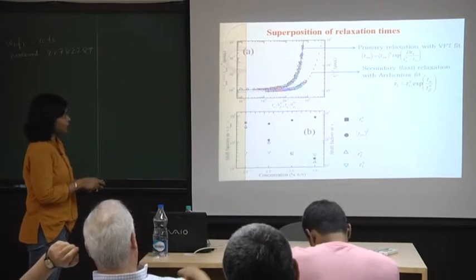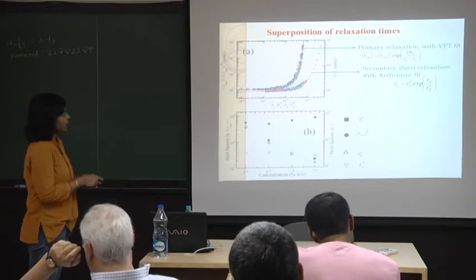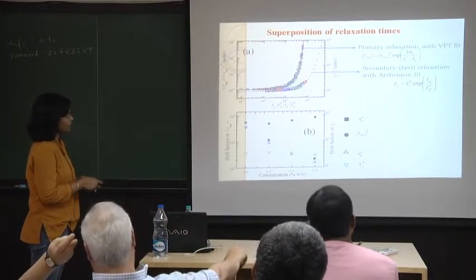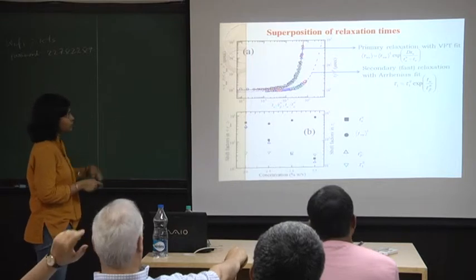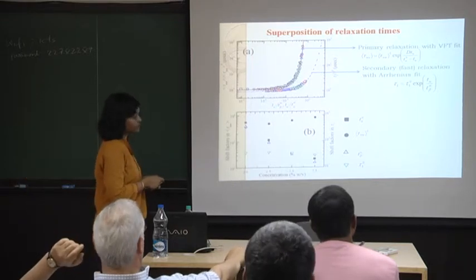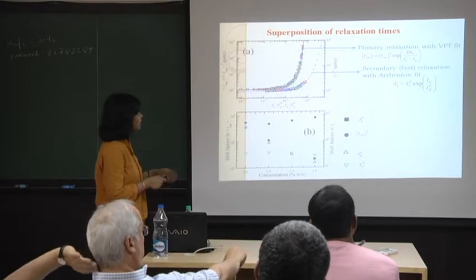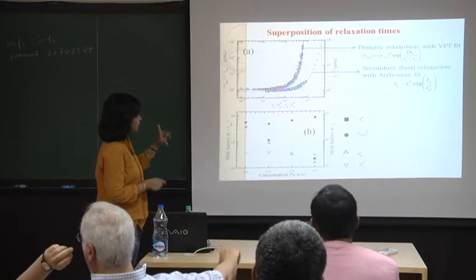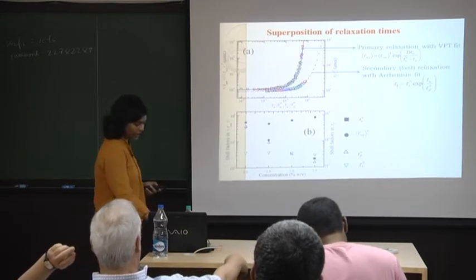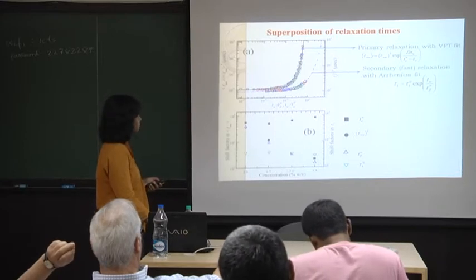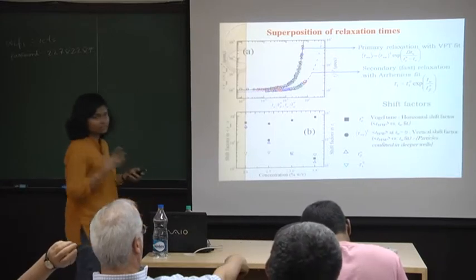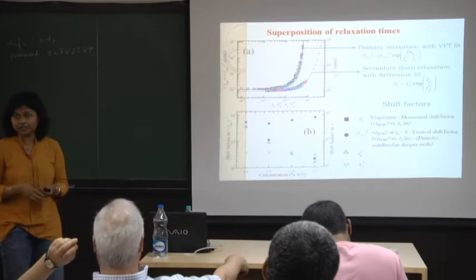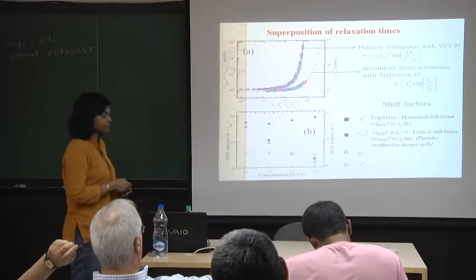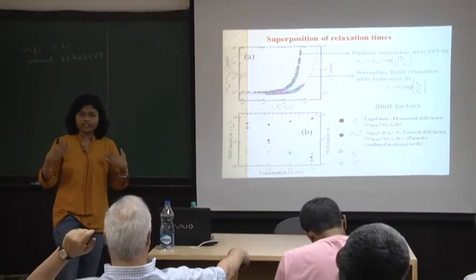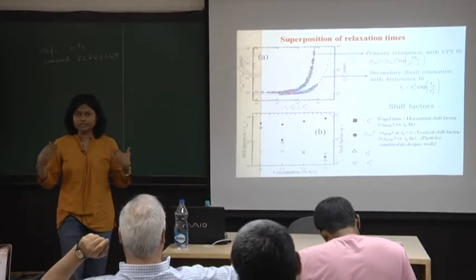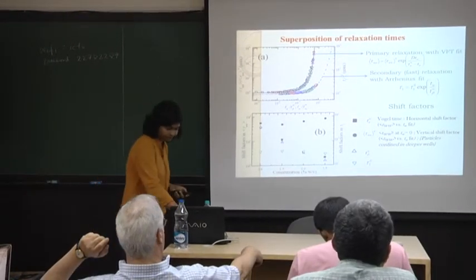You divide the waiting time by this Vogel time, and you get the slow relaxation data. It superposes beautifully, as does the beta relaxation or the fast relaxation. Of course, the dynamical range along the y-axis is much more limited. It tells us a little bit about what is happening within the sample. It tells us that as concentration increases, the structures are being formed inside the sample much, much faster.